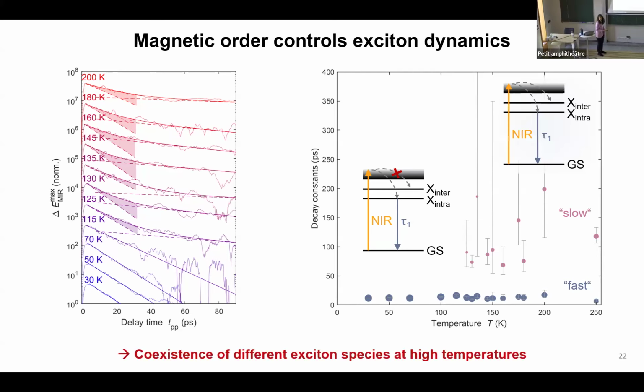However, when we go above the Néel temperature, now we can have both interlayer excitons and in-plane excitons. And on top of that, thermal fluctuations help feed a reservoir of interlayer excitons by pushing the electron and hole pairs across adjacent layers. These interlayer excitons have a diminished overlap between their wave functions, so it takes more time for them to recombine and go back to the ground state. And this is why we have a longer time scale for their relaxation.